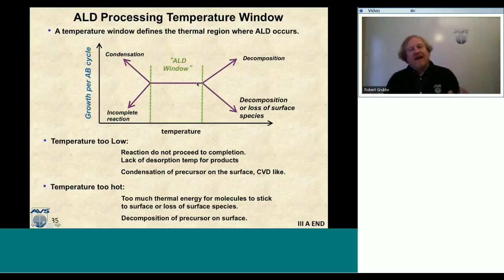Alumina ALD has a very large temperature window. You can do it basically at room temperature or hundreds of C, whereas maybe platinum ALD has a very low temperature window. If you're too hot or you're too cold, it just won't run. It might have a 20 to 30 degree window, thermal window. So the ALD window is an important concept to understand, and also know that the ALD window varies from chemistry to chemistry.